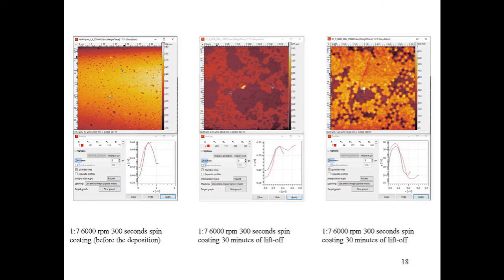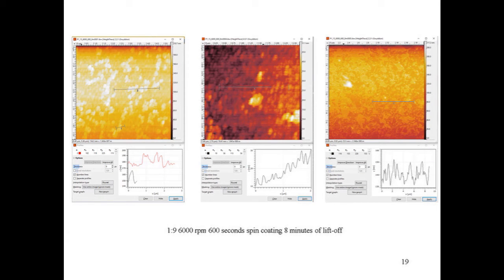And when we look at another example, from before deposition to 30 minutes of liftoff, again, nanospheres under the gold particles were not removed properly. Then we decided to change the proportion of the solution from 1/7 to 1/9. After lifting off for 8 minutes, we saw the same result as the others, which is non-removal of the nanospheres from under the gold particles.